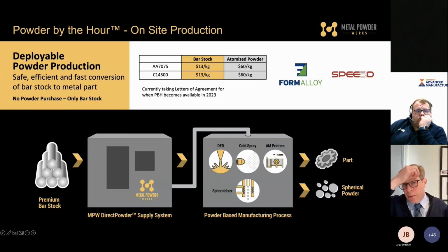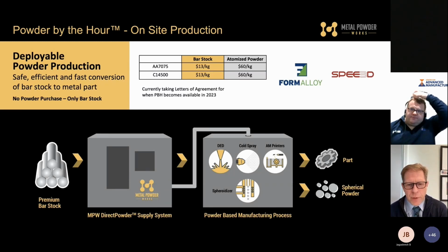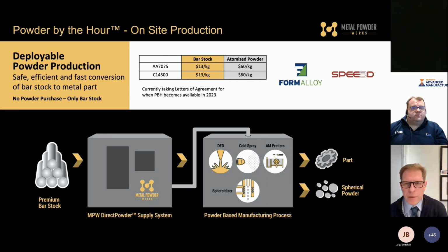So, powder by the hour. This is an idea, a step change, a concept that you were looking at. The idea is that we set our machine down at somebody's site and they feed it with bar stock. Bar stock for 7075 material goes for about $13 a kilogram. You can produce atomized powder for less than $60 a kilogram through that process.